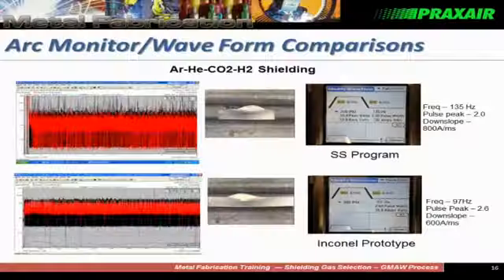What shielding gas changes and waveforms also relate to is arc stability. And arc stability often relates to spatter and control of the welding process. Here we're looking at a standard stainless steel waveform with this particular multi-component shielding gas. And here we're looking at this same material with this different waveform. So again, here's what the weld bead looks like with the stainless waveform. Here's with this Inconel or nickel alloy waveform. You can see the arc stability is much better than it is up here. What's happened here is the frequency of this pulsing has changed from 135 to 97. The height of the peak has gone up. It's a higher peak, but less frequent peaks. So again, tailoring this waveform to a specific material begins to optimize the welding system for this particularly difficult to weld alloy.